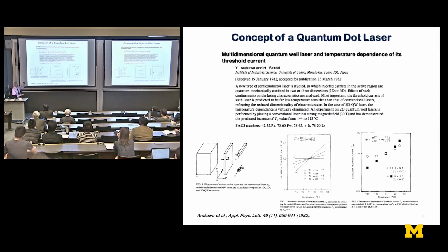And this happens, again, because there are discrete states. The carriers don't thermalize, as in a bulk material. And then, to demonstrate it experimentally, of course, in those days, nobody knew how to get a quantum dot or a quantum box experimentally. So what they did, they applied a very high magnetic field in the z direction and used a high mobility material for the gain region of a bulk laser. So they actually had a double heterostructure laser, and they applied a high magnetic field so that the carriers under this magnetic field actually completed a cyclotron orbit.